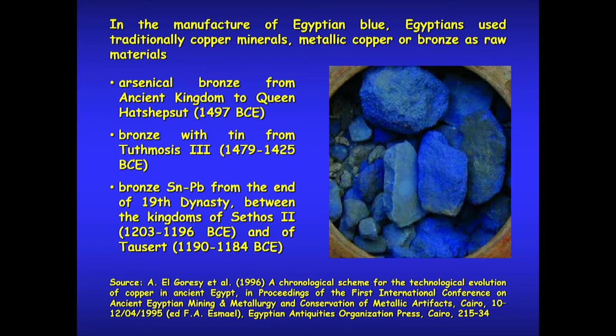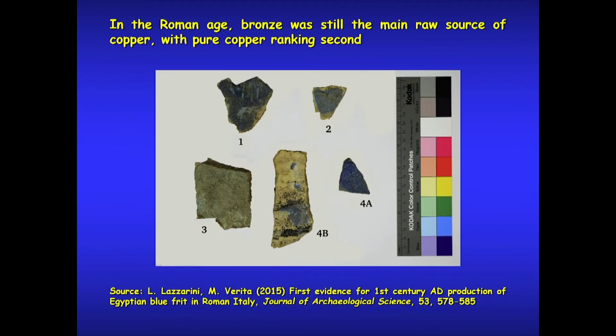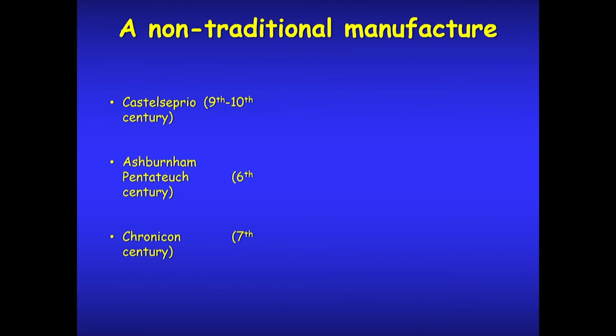The first phase is using scraping of arsenical bronze. The second phase is pure bronze, that is copper tin, and a third phase with bronze with some lead. That is what diagnostics say to us. As to the Roman age, the situation is quite similar indeed. Most of the analytical evidences say that bronze was most probably the source. There are a few data that certify the use of pure copper, for example, the work by Lazzarini and Verità, but nothing beyond these possibilities.